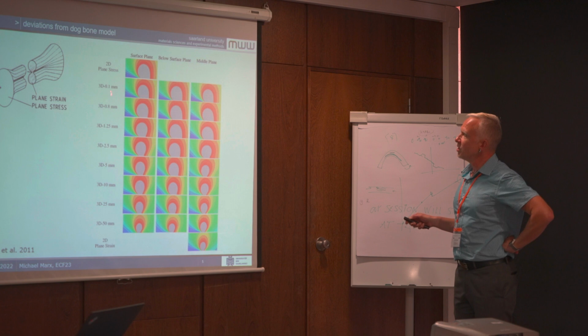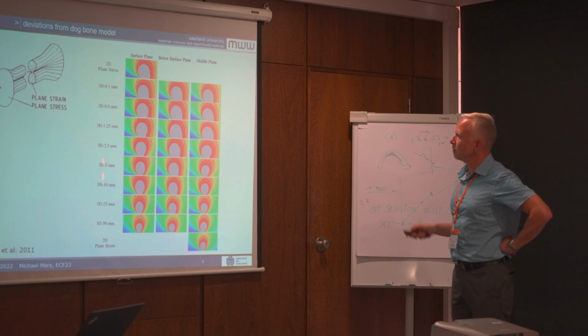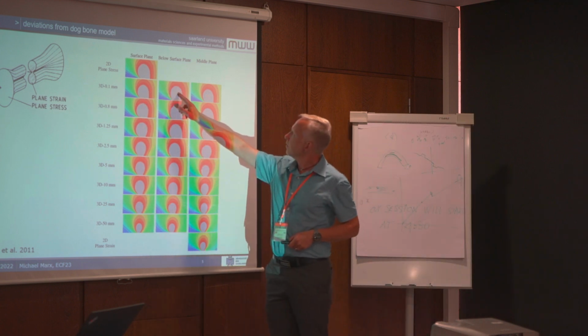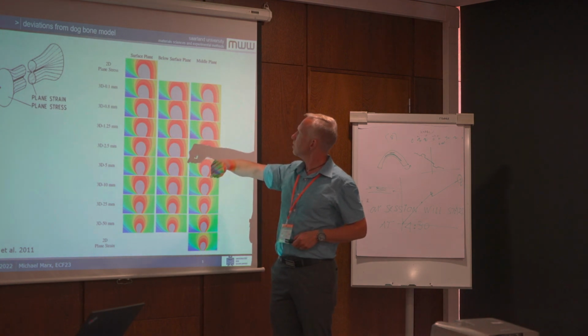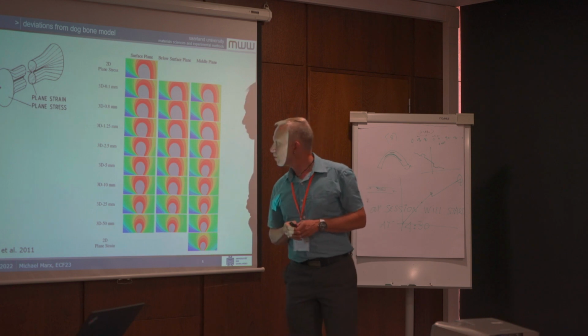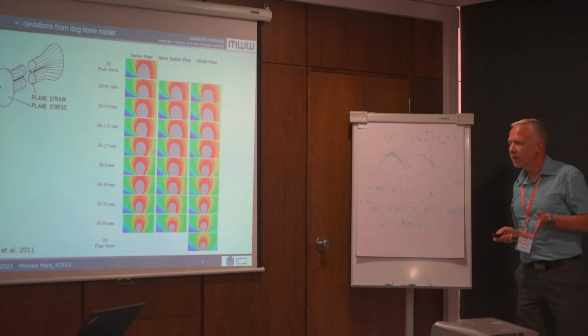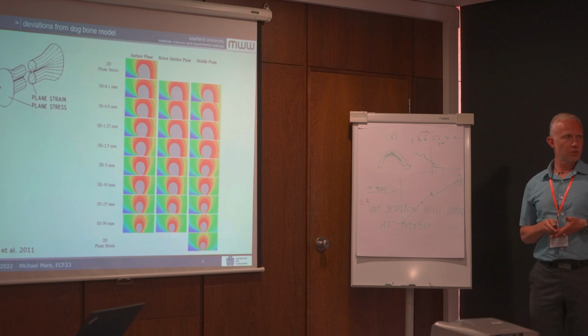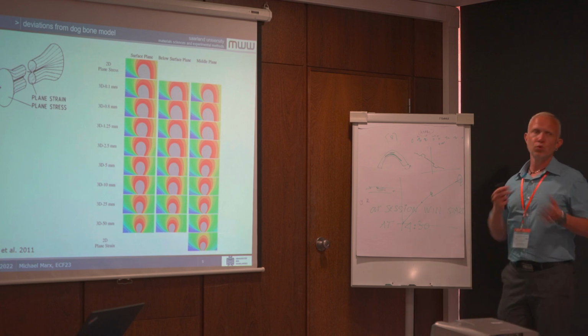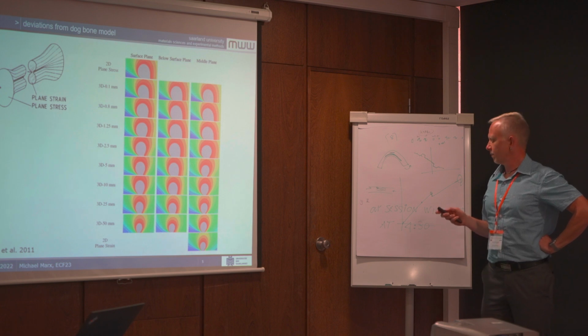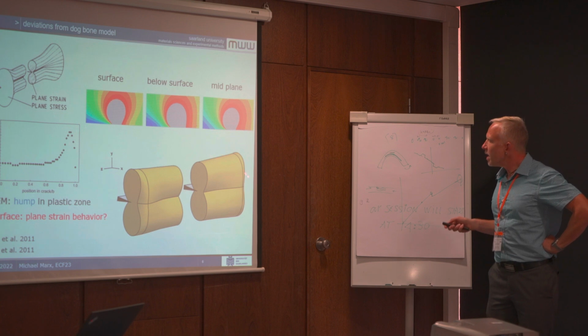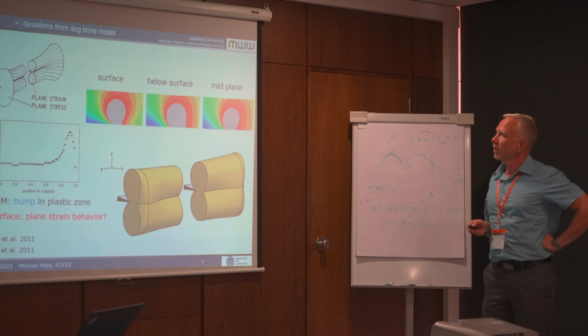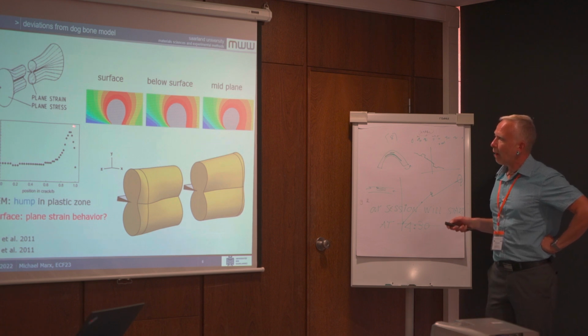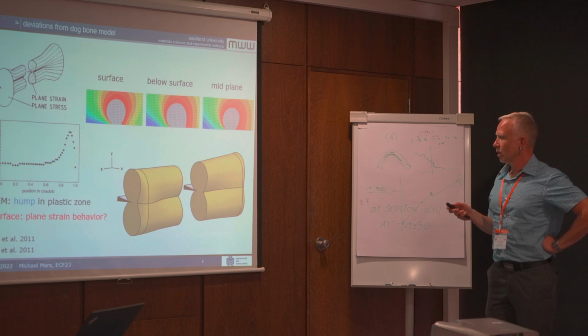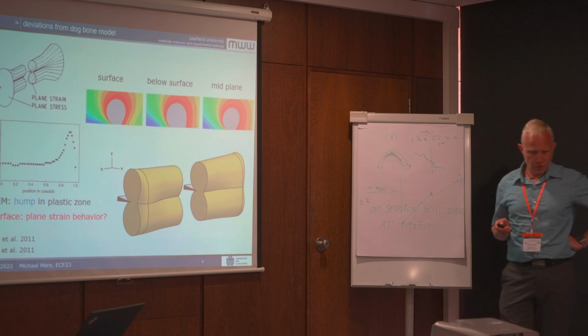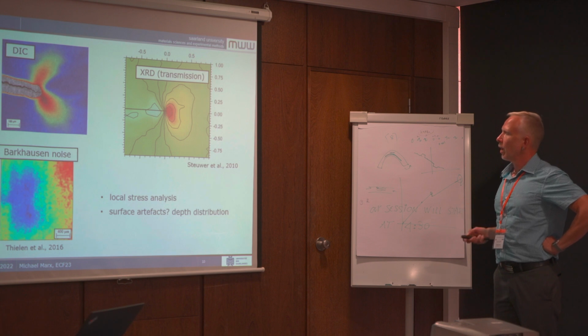But if you make the same for 3D calculations for different thick specimens, then you see this is at the surface and this is below the surface, and the stress distribution increases, and you find this for different thick specimens. So we think that having a closer look at our data from the synchrotron will help us get an idea of the 3D shape of the plastic zone, and this is what we have done with our experiments. So this may be the plastic zone. If you take it from these simulations, you will find something like a hump in your stress distribution and the plastic zone below the surface, and the question is, can we find this also in our synchrotron experiments?